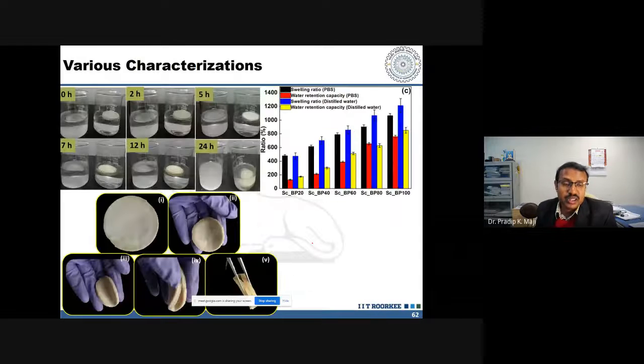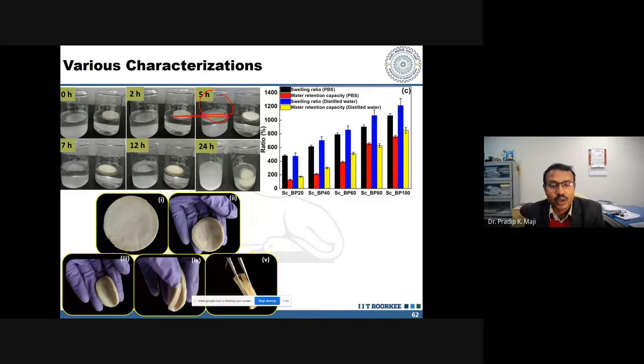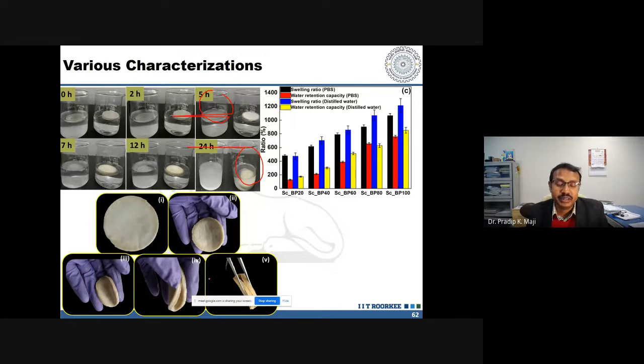Now, if you see what happened in the moist environment: whatever was not able to stand for 5 hours, now you see after 24 hours our material is still in the exact condition. And it is flexible, and this is the visual structure. Whatever I have shown to you, it can be folded, it can be reutilized. And it is very porous in nature.